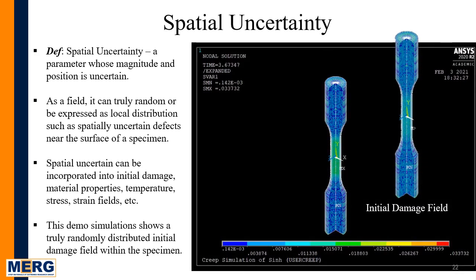In this slide, I am going to show you the spatially distributed initial damage field. Spatial uncertainty is a parameter whose magnitude and position is uncertain, and it can be truly random and can be expressed as local distributions such as spatially uncertain defects near the surface of a specimen. And this spatial uncertainty can be of initial damage, material properties, temperature, stress, strain fields, etc. These demo simulations show a truly randomly distributed initial damage that is evolved from an initial number to unity at the rupture of the element.